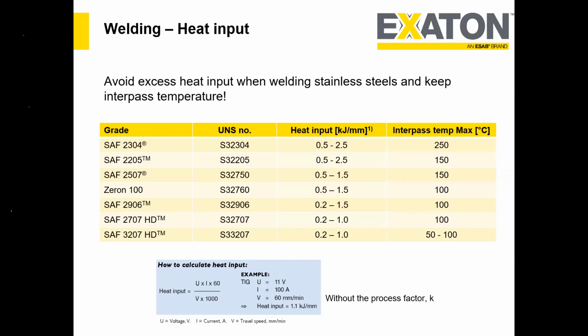One, it has a tendency to form chromium nitride. And in the microstructure, if it cools down faster, you'll have more ferrite, because liquid transforms to delta ferrite, and the ferrite will not have enough time to transform into austenite, so you'll get more ferrite. If you get more ferrite, what is the disadvantage? Your toughness property will be down. You could have a slightly better corrosion property, but your toughness or impact property will be low.